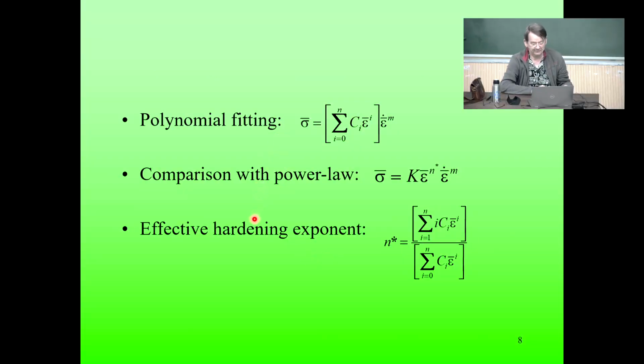In that work, what I'm presenting, polynomial fitting of the strain hardening curve was used in order to have an analytical formula. As I said, everything has to be analytically written so that the mathematical perturbation theory can be applied on it. The one is the hardening. So we fitted with a polynomial where the Ci are the coefficients of the polynomial and the epsilon i is the exponent. So for a number of about 20 or 50 coefficients, they describe very precisely. It's a simple mathematical description of any curve.